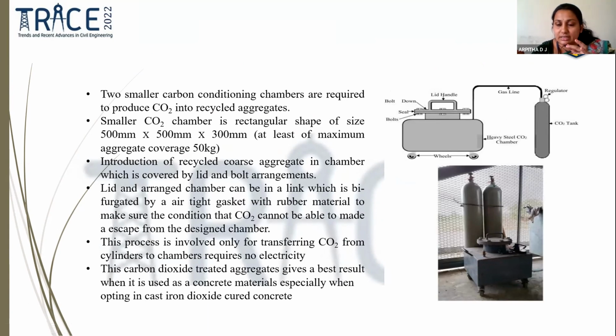This is the conditioning chamber for recycled aggregates. Here we will condition the aggregates by pouring them in and passing the pressure of carbon dioxide from this cylinder to this chamber, with the lid and a complete tight arrangement, fitted with airtight management. There is no escape of the carbon dioxide to the outside environment. Here the recycled aggregates are cured. Next slide.